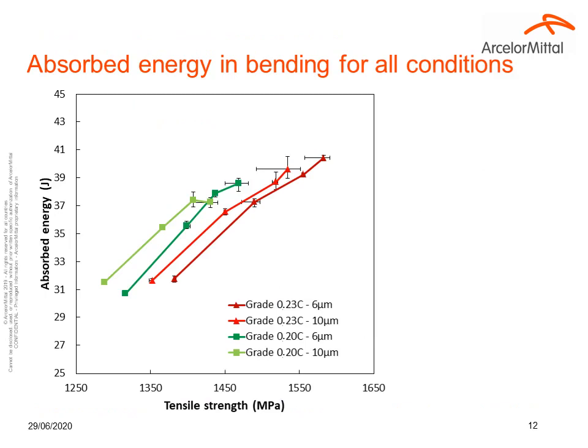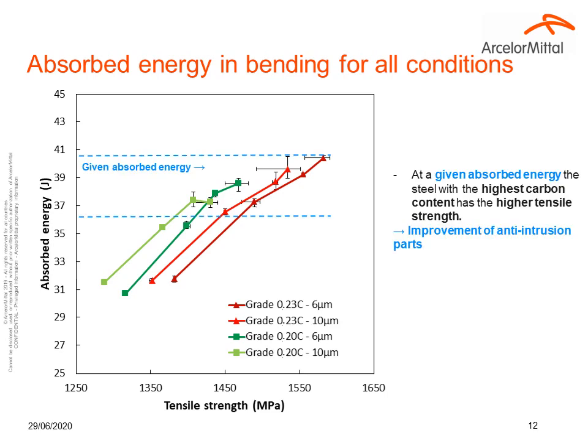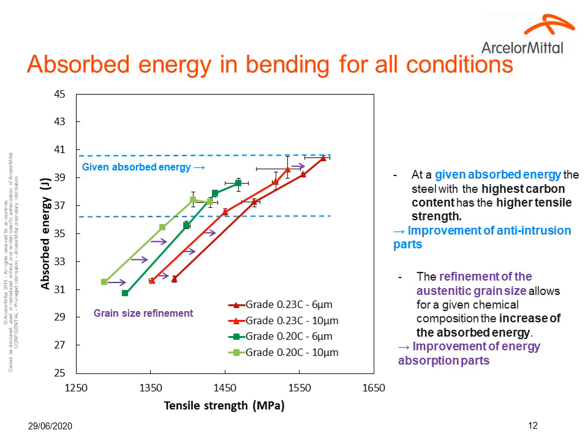The absorbed energy in bending is now represented for all the different conditions and not just for the four groups. So you can observe the evolution of the absorbed energy versus the tensile strength. If you look at a given absorbed energy, the steel with the highest carbon content has the higher tensile strength. This could be an improvement for anti-intrusion parts due to the higher tensile strength.